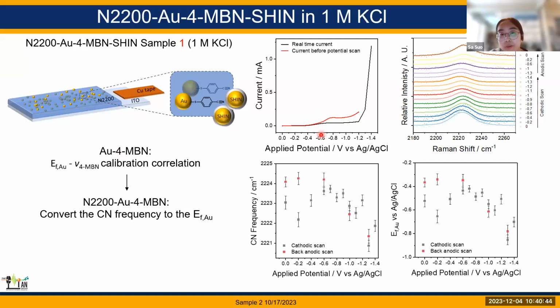So we did a similar experiment. We apply potential from 0 to negative 1.4, and we can see how the CN frequency changes. After fitting, we also summarize the nitrile frequency as a function of applied potential. We can see that before the reduction of N2200 happens, the nitrile frequency is not that dependent on the applied potential. Actually, this data is not that good, but we'll do more experiments about this. But after the reduction, we can see a solid shift of nitrile frequency. And if you look at the red dots over here, which is the back anodic scan to prove that this trend is real, we can see that during the back anodic scan there is also a shift and then plateau trend being observed.